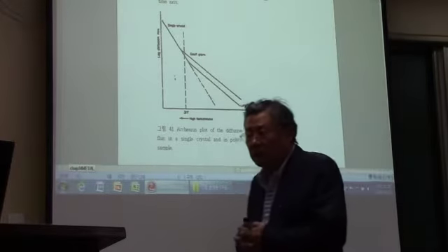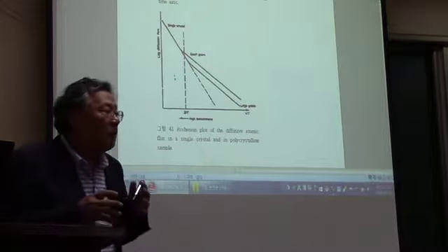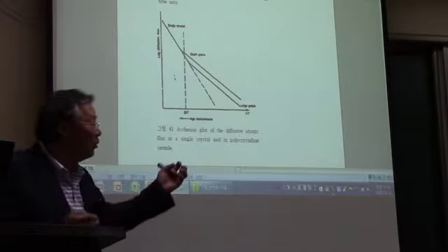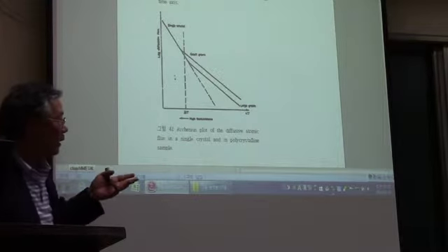So if you add copper beyond the solubility limit into aluminum, you're going to have precipitation, and those precipitates preferably form at the grain boundaries, and they will block the atomic motion in electromigration.